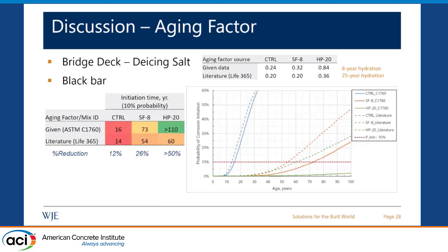So with the literature aging factor, we get a reduction of 12% in the predicted service life, and if we are using the control mix, it's even higher. With the silica fume mix, and it's more than 50% reduction for the natural pozzolan. So this highlights the importance of thinking about how you're interpreting the lab test results, what are the appropriate assumptions for some of the input parameters. Here we're given an example of aging factor, but that could be true to other input parameters as well.